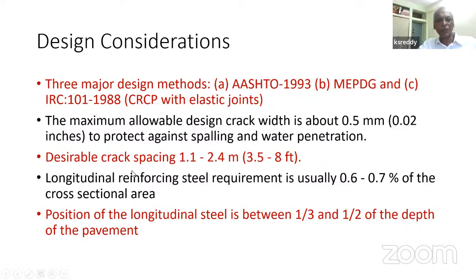And the desirable crack spacing should not be smaller than 1.1 meter, and that is 3.5 to 8 feet. If it is smaller than this, your punch out problem is going to be more because you got very narrow slabs and there is more potential for punch out cracking. If it is too large, very long slabs will contract more. The crack is going to be opening more. So you have more problem of joint spalling, breaking of the crack edges is going to be more if you got long slabs. So you don't want your crack spacing to be greater than 8 feet. You don't want the crack spacing to be smaller than 3.5.